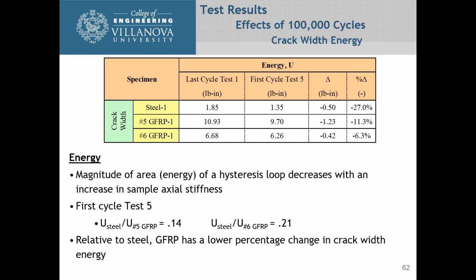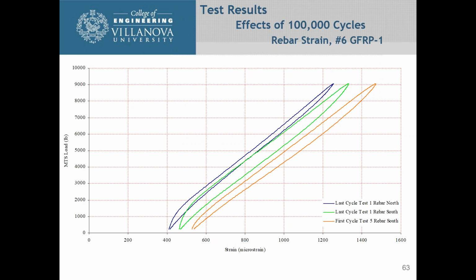So the magnitude of the area of the hysteresis loop decreases with an increase in the sample's stiffness. And so you could see that the energy for the steel divided by the ratio of the steel to the number 5 bar was 0.14, and for the number 6 bar was 0.21. So relative to the steel, the GFRP has a lower percentage change in crack width energy. So let's take a look at the strain.